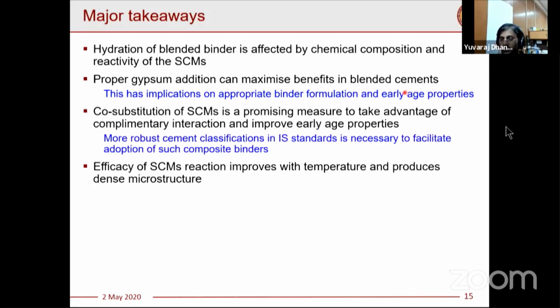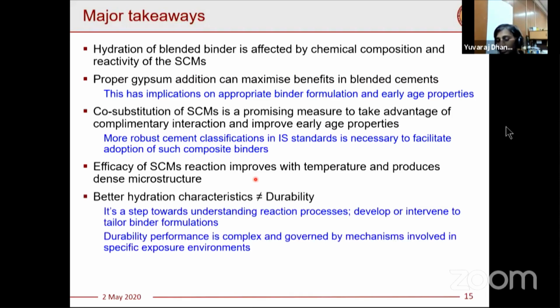Co-substitution of SCM is a very promising measure to take advantage of complementary interactions. And this obviously necessitates that IS standards should facilitate adoption of such composite binders in due course of time. And the efficacy of the SCM reaction improves with temperature, and this could have a major impact on the microstructural development.